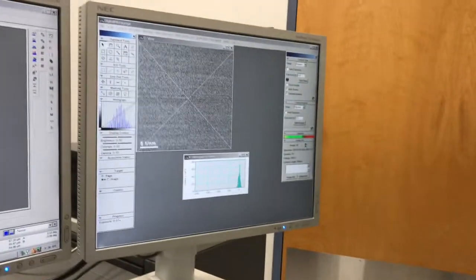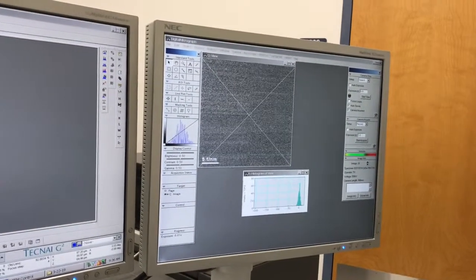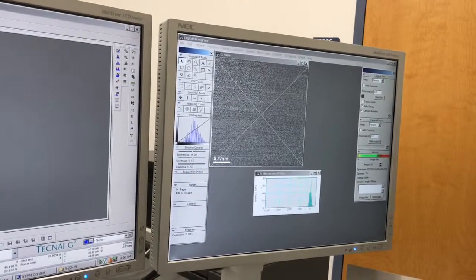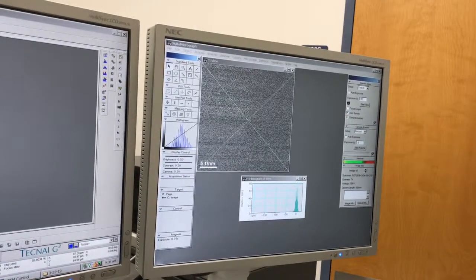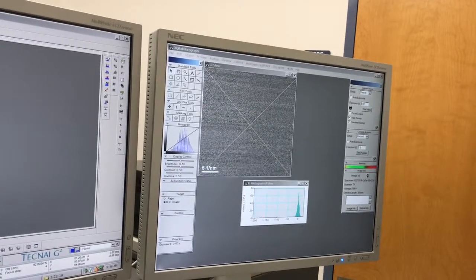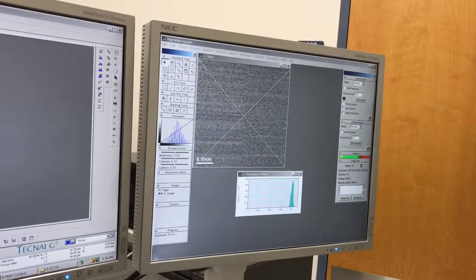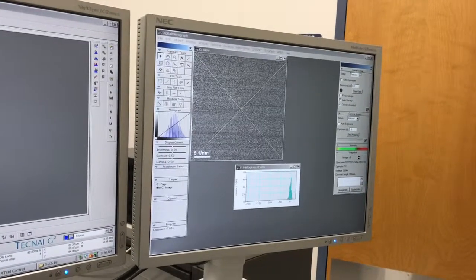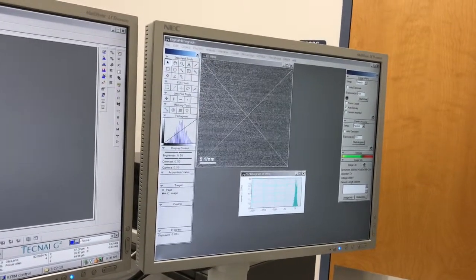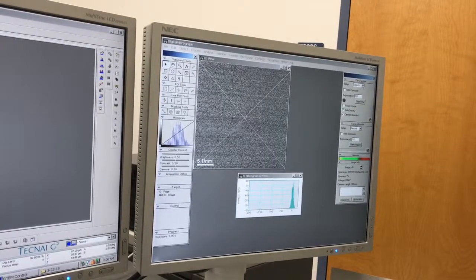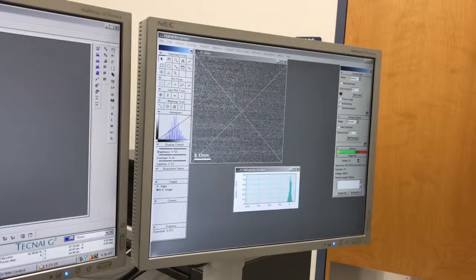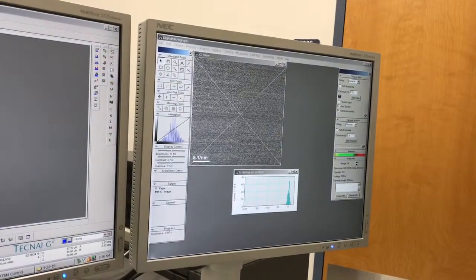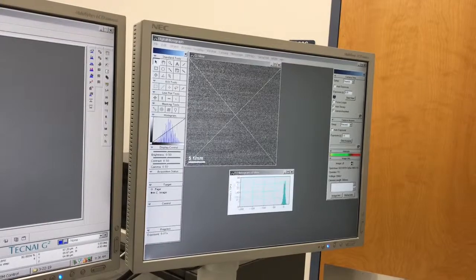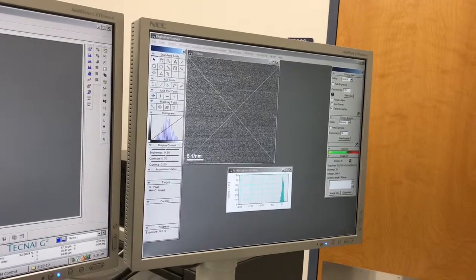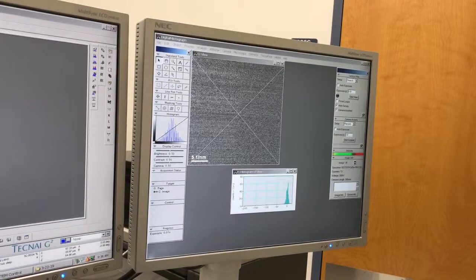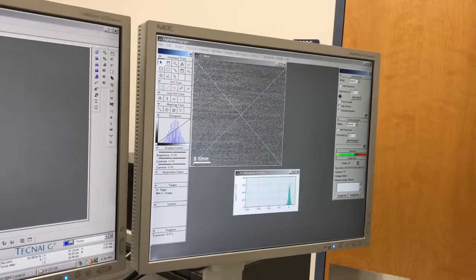When we talk about recording conventional images, bright field, high resolution images, we're more or less not overly concerned with damaging the camera. It's very difficult, unless you're being extremely negligent, to damage the camera while acquiring a conventional image. What you tend to be more concerned with when choosing an exposure time is making sure you get adequate signal to noise, but you're balancing that against instabilities of the specimens. In other words, drift, as we saw before.